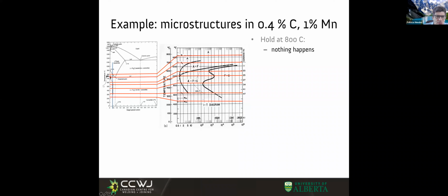If I do a quench to this other temperature that is just above the A1 line, the line at which no austenite could exist, what do we see? We see that we would have transformed primary ferrite. These TTT diagrams all have different name conventions, so you have to know what to expect. This says A plus F - that means you have austenite at the beginning that is like gasoline in your car, driving the motion. The austenite started to transform here at this point, the start of transformation. As time goes by, it's transforming into ferrite, just above this line. Is it going to finish transforming? Never, because there will be austenite always forever retained there.